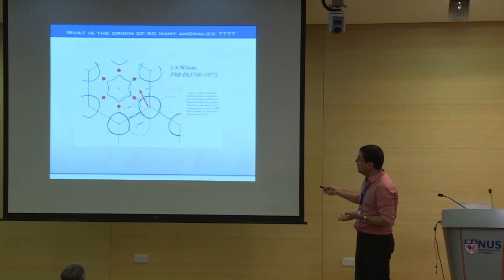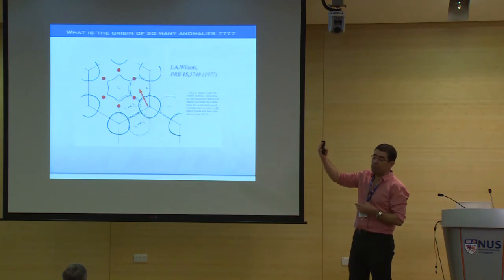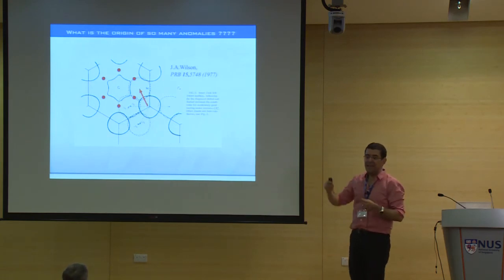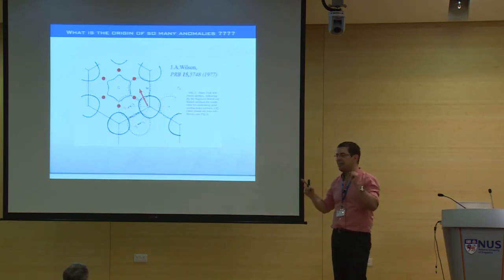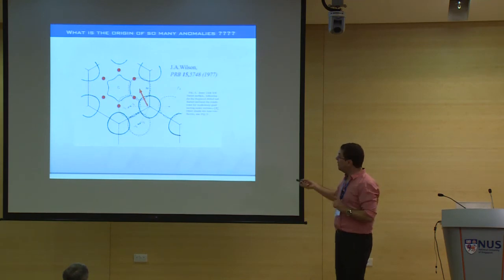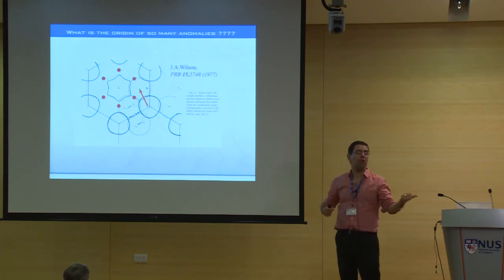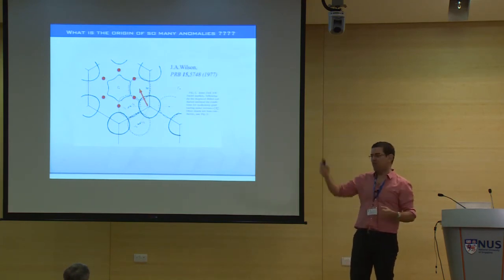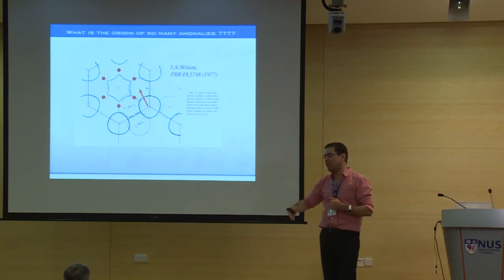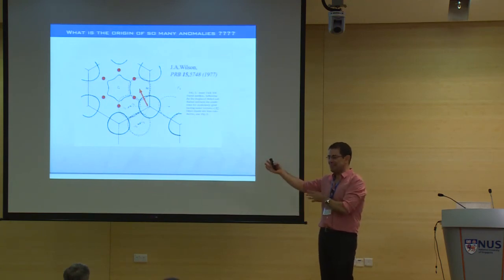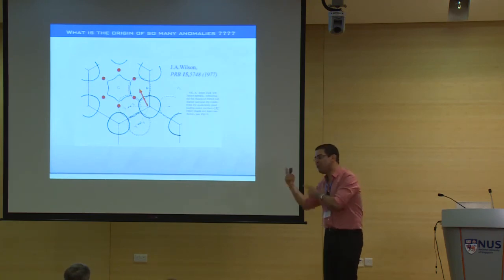Some people thought actually that the transition was driven by these van Hove singularities because there you also have a very large density of states. And actually, this would explain the contradiction between the susceptibility and the resistivity. Why? If you gap a region with very large density of states, the electron phonon scattering rate goes down very fast. So essentially, you kill the electron phonon scattering, but you keep the system metallic. So you can reduce the density of states, but reduce the scattering faster than you reduce the density of states.